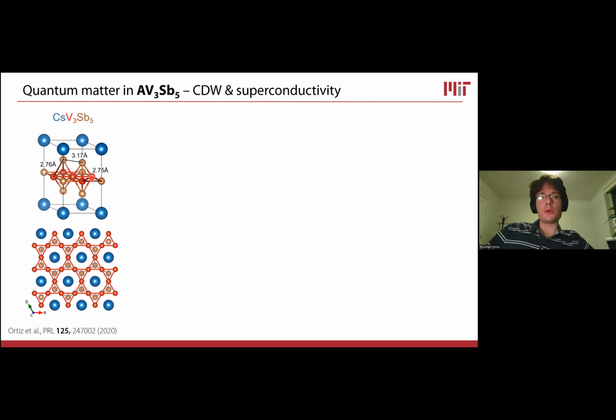This is the side view of the structure. So you have this sort of tetrahedral cage of alkali metals, and within this cage there are these Kagome planes, where the vanadium atoms are the ones that form the Kagome sublattice, and part of the antimonies are in the planes, and part of the antimonies are coordinated out of the planes. So it has this a bit peculiar 135 stoichiometry, but the important thing is that structurally speaking, this is a layered system. And the fundamental unit of this layered system is the 2D Kagome network, and the atoms that are occupying the Kagome sites are the vanadium atoms, which is important because the system has a lot of multi-orbital physics that has to do with the different 3d orbitals that are brought in by the vanadium atoms.